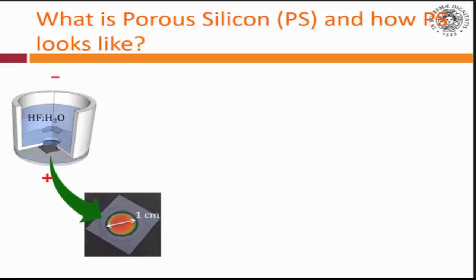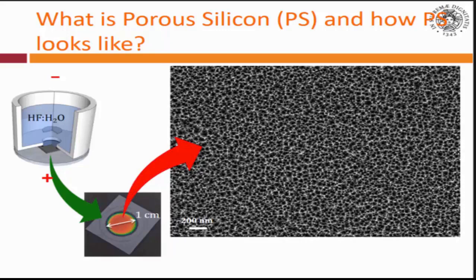You just take a silicon substrate, put it in an electrochemical cell with water and some trace of hydrofluoric acid, and if you source current with silicon as the anode of the electrochemical cell, then the silicon dissolves. The way it dissolves really depends on the etching parameters. If you take P++ silicon, what you get is random dissolution. If you increase the resistivity of the substrate, you can control the dissolution down to half a micron in size.